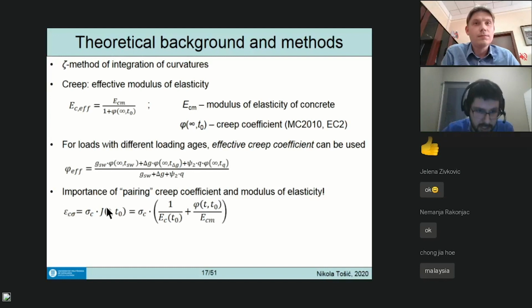These are things that should be taken into account. What's important is the compliance, because in the end it's what gives you the strain. But within it, you need to be careful which values you are pairing together. So when dealing with the model code, if we calculate the creep coefficient according to the model code, we need the modulus of elasticity here at 28 days.